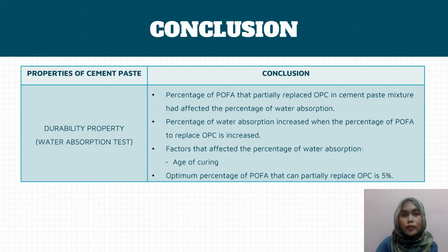And the third objective is to analyze the durability property of cement paste by conducting water absorption tests. It can be concluded that the percentage of POFA used as partial replacement of OPC has affected the percentage of water absorption. This is because the percentage of water absorption will be increased when the percentage of POFA increases. The percentage of water absorption has also been affected by the age of curing. As the age of curing increases, the percentage of water absorption decreases. This is because as days pass by, the voids and the porosity of the hardened cement paste have been reduced, thus less water is absorbed by the hardened cement paste. To conclude, the optimum percentage of POFA that can partially replace the OPC is only 5%.